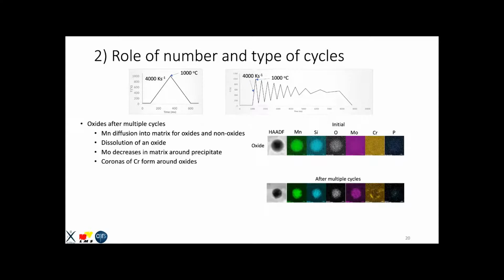So we have the same first cycle, but here now we have added more cycles. In general, there were more changes because of this additional cycling, but the biggest difference is we saw that Mn diffusion was happening from both oxides and non-oxides. We found that one of the oxides actually dissolved completely into the matrix. The content of molybdenum, which was originally not significant in these oxides, in fact started getting stripped away from the surrounding matrix, leaving behind the same molybdenum content inside this precipitate.